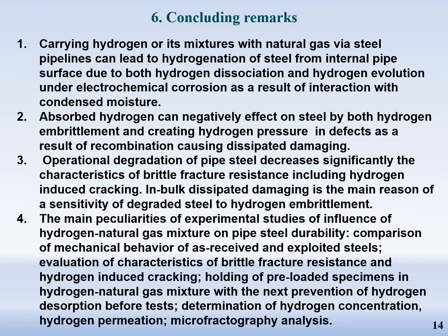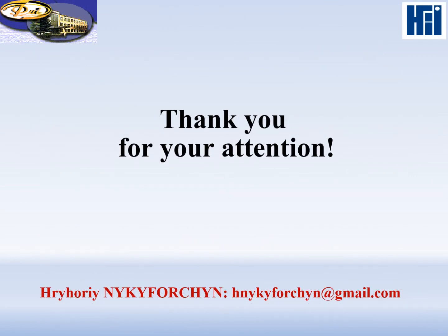Operational degradation of pipe steel decreases significantly the characteristics of brittle fracture resistance, including hydrogen-induced cracking. In-bulk dissipated damaging is the main reason of a sensitivity of degraded steel to hydrogen embrittlement. And finally, the main peculiarities of experimental studies of influence of hydrogen natural gas mixture on pipe steel durability: comparison of mechanical behavior of as-received and exploited steels; evaluation of characteristics of brittle fracture resistance and hydrogen-induced cracking; holding of preloaded specimens in hydrogen natural gas mixture with the next prevention of hydrogen desorption before tests; determination of hydrogen concentration, hydrogen permeation, microfractography. Thank you for your attention.